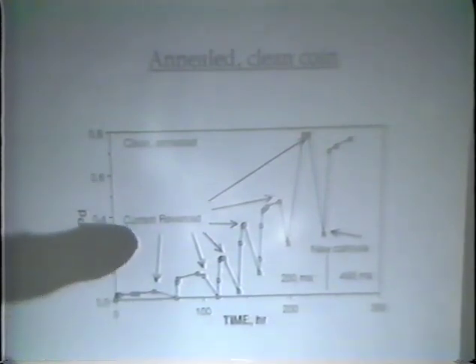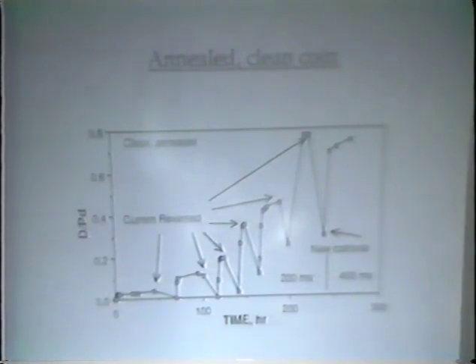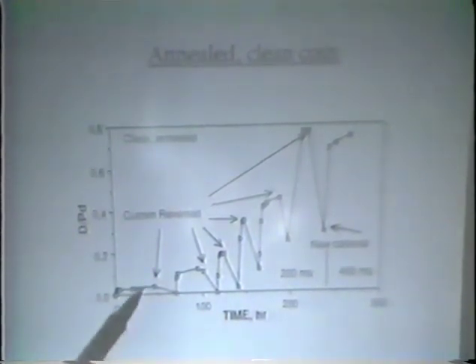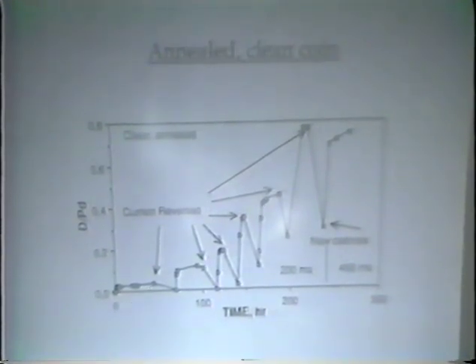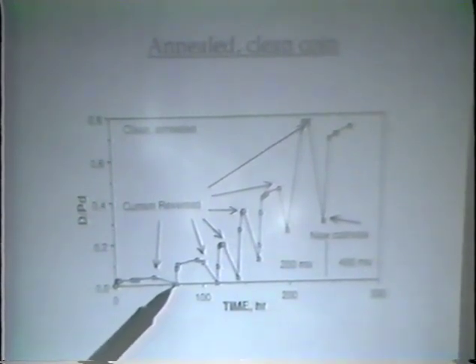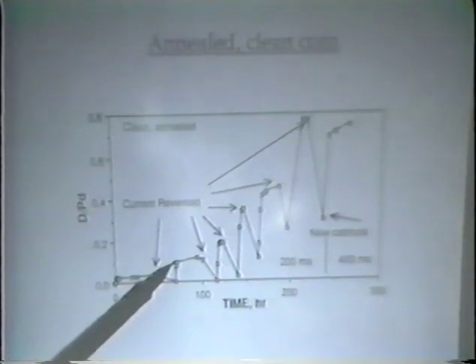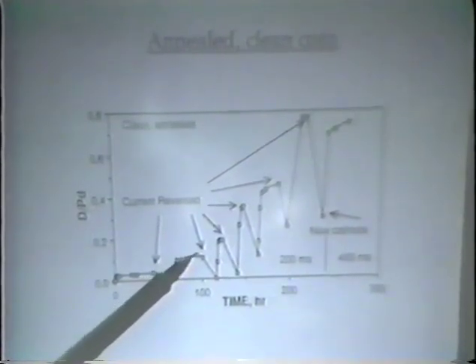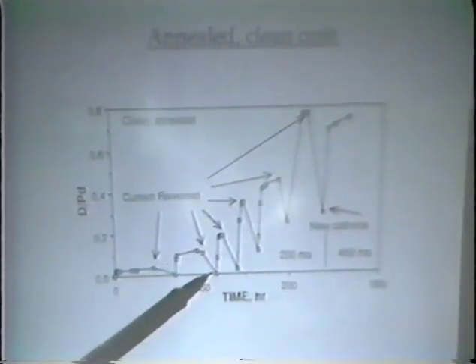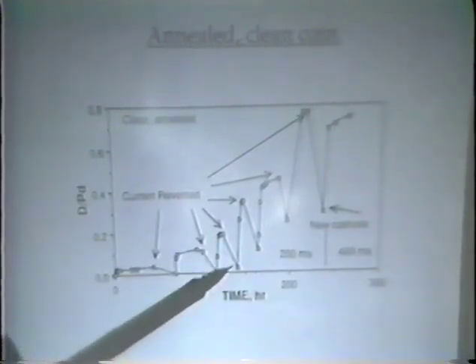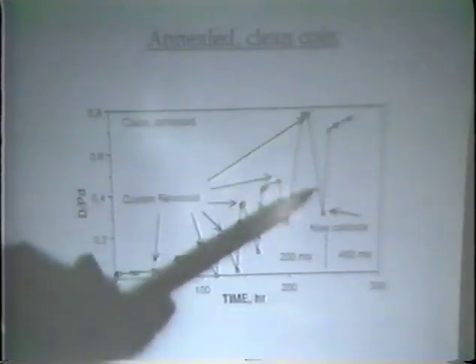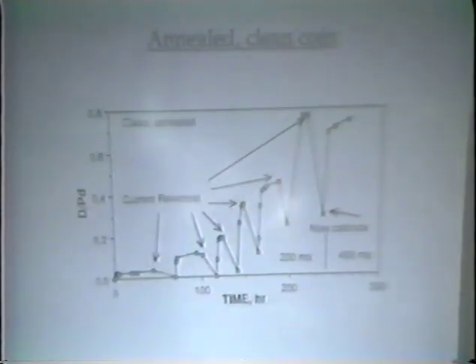When we first started putting deuterium in, nothing happened. It took up just a little bit, and pretty soon exhausted our patience. So we, at this point, reversed the current and to here, and then returned the current back on again, and you'll notice it went up nicely and hit a new plateau. Reversed the current again. It went up still higher, and you'll notice that each time this was done, it went to a still higher value.